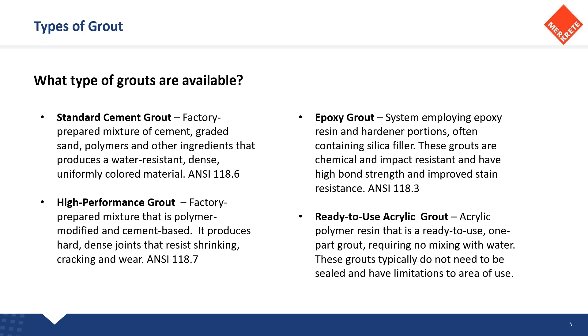Standard cement grouts typically come with some precautionary items — they're a little bit more water sensitive, meaning the exact amount of water you're mixing and cleaning with matters. They're a little less forgiving than some of the other grouts. Then we have high performance grouts — ANSI 118.7 — and I'm so happy to see the industry really trending toward these. High performance grouts are a factory prepared mixture that is polymer modified and cement based, but there are additional things we're putting into these.